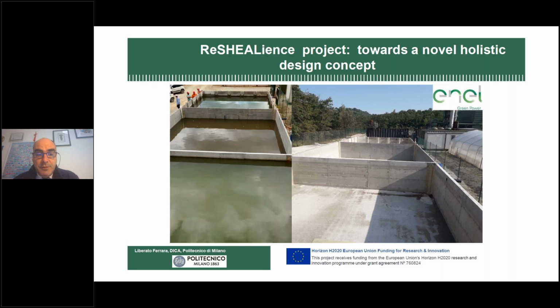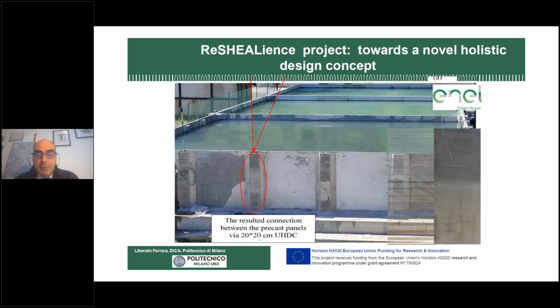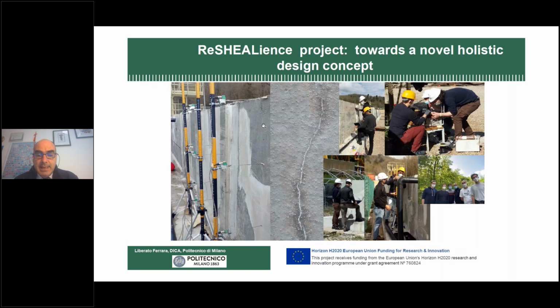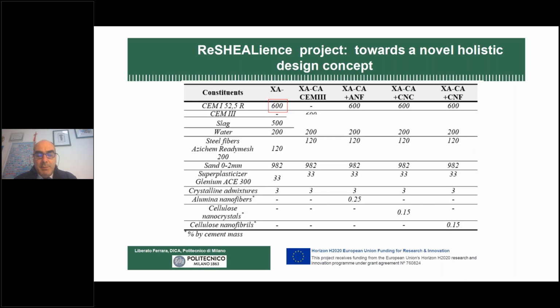And these are some images of the finished basin and of load tests that we have been regularly performing and monitoring. You can see here the basin is completely filled, and you have some pictures here on the right. It's a little bit blurred, but it's the degradation of our ordinary concrete exposed to sulfate water, and our UHDC material, which is very smooth and completely sound. And some pictures also show a quite large crack, a shrinkage crack, which was completely healed with no detriment to the water containment capacity.